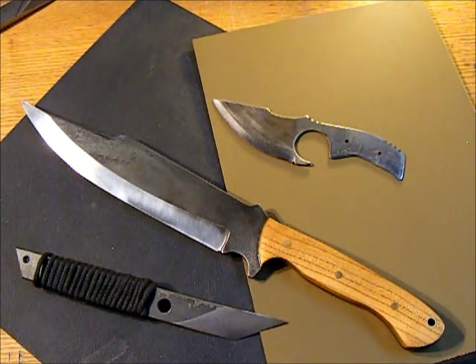Oil quench it. Make sure you have the oil heated to 150 to 200 degrees. I found with this one, the colder end of 150 was better because the blade is so thick. You don't want it to cool down too slow. So yeah, I did around 150. Your smaller blades, if you're using O1, get it up towards the 200 mark for your oil. Reason being, then you won't see as much warpage. Warpage is bad, especially when you spend 4 hours on a blade and you warp it and it's done.